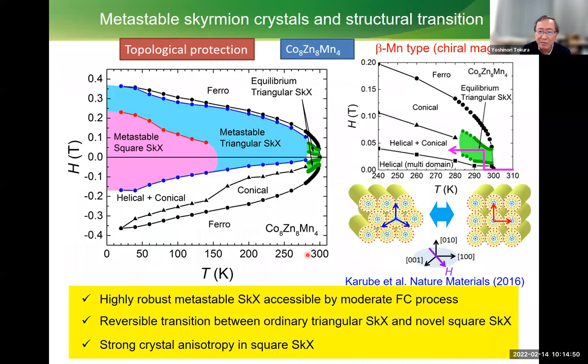And this metastability of the skyrmion is one of the great advantages, or great natures, of the skyrmion itself. For example, if we make a much higher temperature skyrmion system, for example in this beta manganese type compound, it's also a chiral structure. Its TC is around room temperature, sometimes exceeding 400 K. But also the skyrmion always appears at another high temperature, close to the magnetic phase boundaries. The other region is all helical state, where the conventional single Q state is realized.